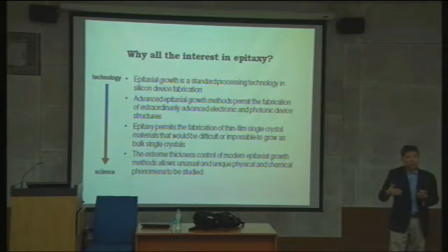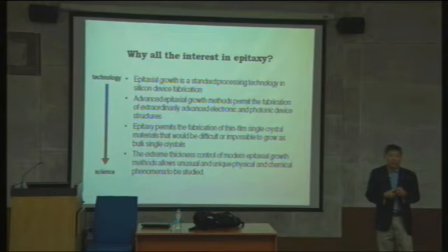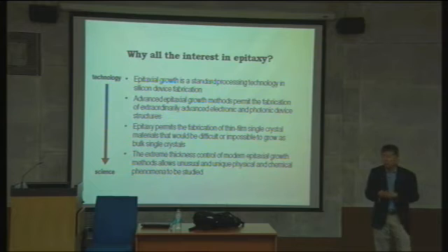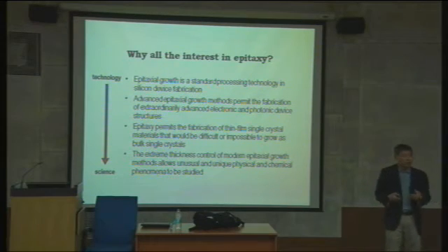I have a lot of examples of forming metastable phases. For example, strontium iridate is a very interesting spin-orbit coupling material, because iridium is a 5d element, and there's strong spin-orbit coupling due to its high Z number. At room temperature, that material has a monoclinic structure, a very complicated monoclinic structure. When you go to extremely high pressure, like 10 gigapascals, it goes to the orthorhombic, perovskite structure. So the perovskite structure doesn't exist at ambient pressure and temperature. But by growing this material on top of a perovskite substrate, we can grow the perovskite structure, which is only possible at extremely high pressure. So that is something you can do: what is difficult or impossible to grow as a single crystal, we can do in this system.